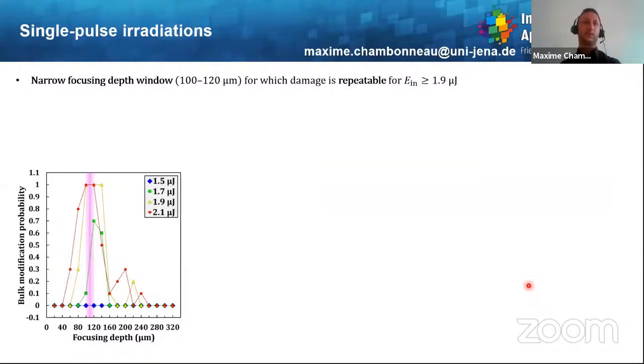So we have carried out single pulse irradiations, and here are the results in terms of modification or damage probability in the bulk of silicon as a function of the focusing depth. One can see that it is absolutely non-monotonic, and one can reach 100% damage probability inside the bulk of silicon, so repeatable modifications at focusing depth around 100 to 120 micron. And of course, you need some sufficient input pulse energy, so higher than 1.9 microjoule.